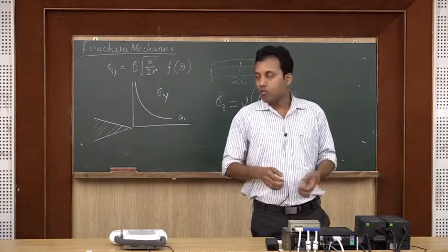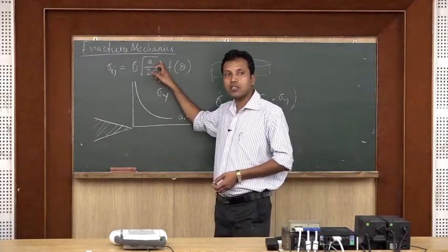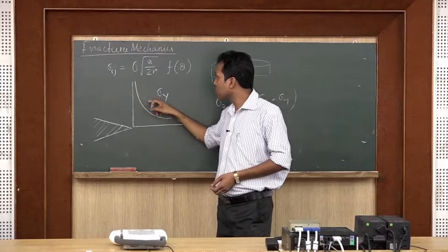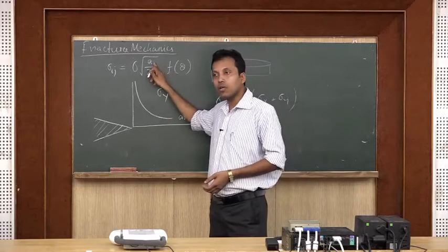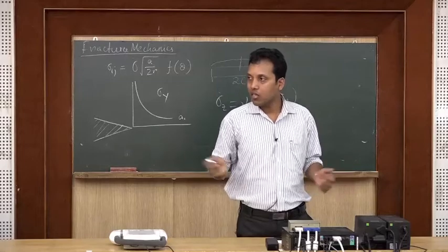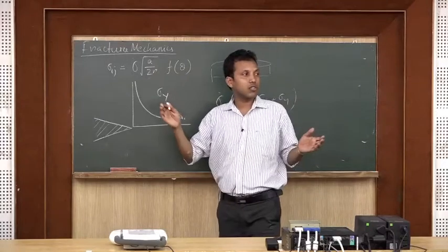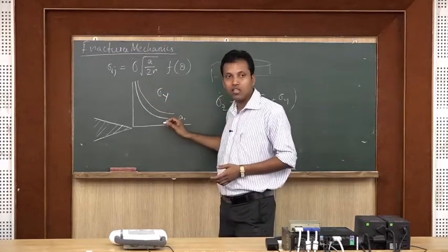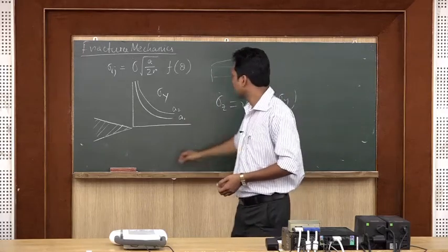Okay. Anyway, so what we can see from here is, if the crack length A increases, then the distribution of sigma y will change, isn't it? Because it is in the numerator. So, what I will have now, the stress concentration term etc. will increase, isn't it? If the crack length increases, then the stress concentration everything will increase, and I will have another distribution of this manner, that I think you can follow. For a crack length of A2, this will be the stress distribution.